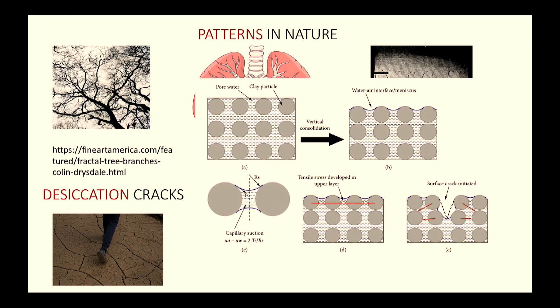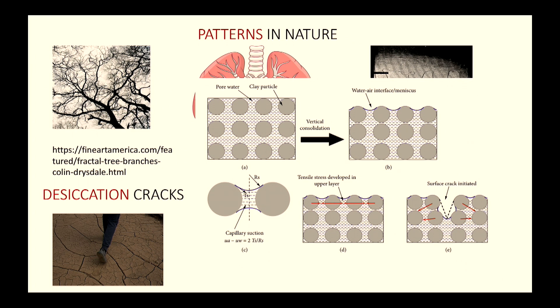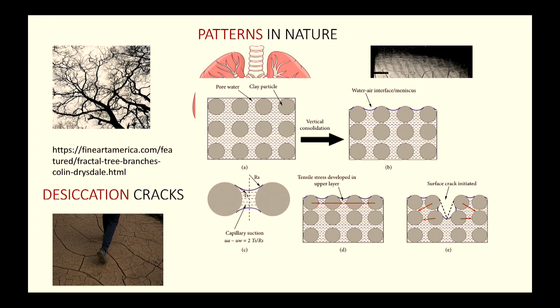Cracks form because: clay is a gel with water in its pores. As evaporation occurs, vertical consolidation makes the sample thinner; a meniscus forms and pore pressure increases due to tiny pores (maximum micron-size, so capillary pressures are huge). Tensile stresses develop in the top plane and surface cracks form.